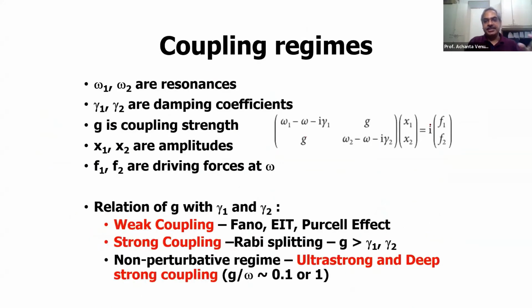So here the structure is made of these split rings on a stretchable PDMS material. By stretching, we are slowly deforming the shape of the split ring, which leads to scattering of the light, and these two resonances are excited. So both the modes split into two orthogonally polarized states. In this, I've not shown the spectrum, but here at S equal to 0.1, for example, in the weak coupling regime, the stretching is smaller, so you see enhancement in transmission. And as you keep increasing the stretching, the deformation of your split ring profiles, you see this splitting. So in the weak coupling regime, you have the EIT, and in the strong coupling regime, you go to this Autler-Townes splitting, or splitting of these energy levels. So in one system, you can see both of them.